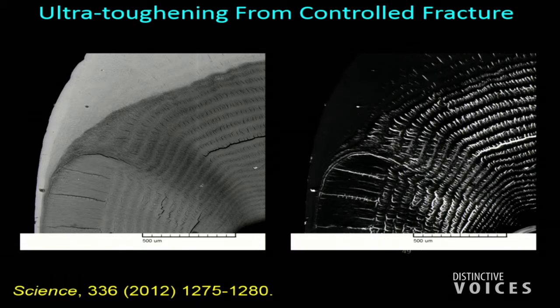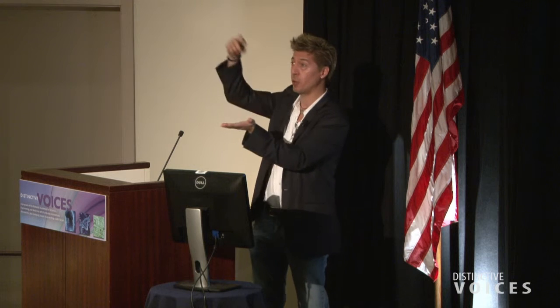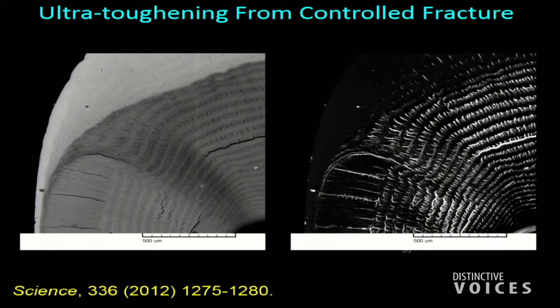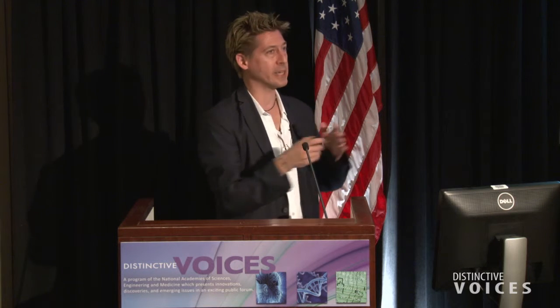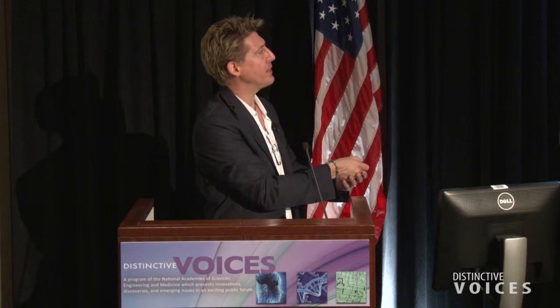This periodic region has a lot of nano cracks. How we got this is we put this club under an electron microscope, and we let the beam just sit there and charge. Anytime you have some high surface area material, it tends to charge up. The electricity essentially can't escape out of the club. So all these little wire-looking structures are cracks. I mentioned earlier that engineers build things so strong that when they fail, they fail catastrophically. Biology has a different strategy. It says, well, let's build it strong enough. There will be cracking here, but none of these cracks leave the club, so it stays intact. And remember, this is after tens of thousands of impacts.